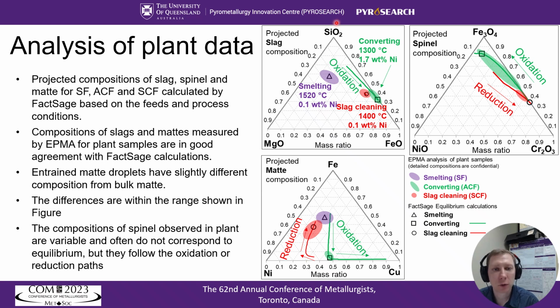The simplified process model, based on FactSage equilibrium calculations, described well the trends in slag, in spinel, and in matte compositions. Of course, the plant data samples showed a range of compositions, especially for spinels, but the compositions of observed spinels followed the oxidation reduction path as predicted by the model. FactSage calculations also provided the process conditions such as oxygen and sulfur dioxide partial pressures, which cannot be measured directly, but were useful for further analysis.